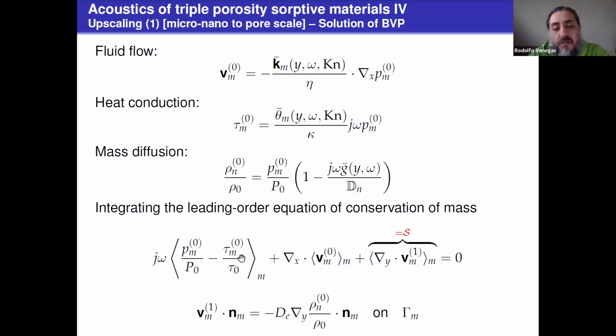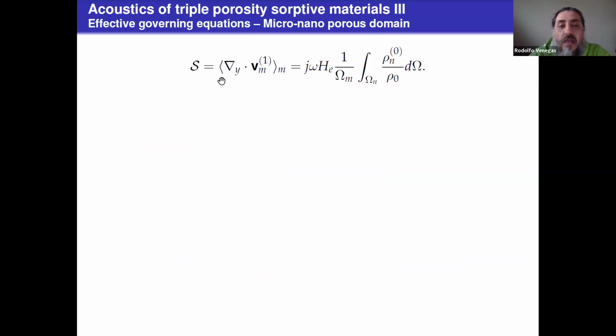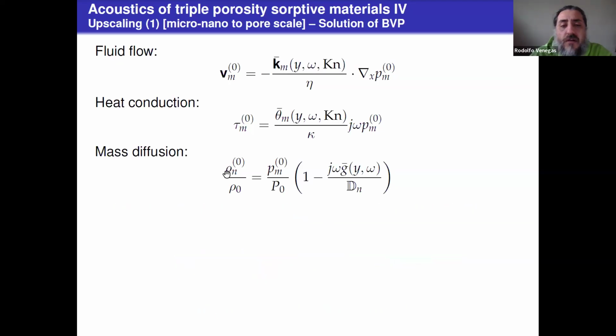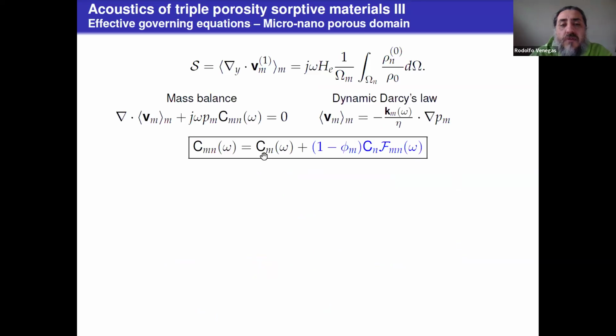So we take the average of this equation, and then we identify the source term. And this is very important because normally this term is zero for conventional materials, but in this particular case, we have the effect of what's happening at a smaller scale coming from this term. And in particular, this term can be written in this way. And then when we take the average, we use the divergence theorem, and then we can write this divergence of velocity in terms of rho n, and rho n is already known, which is given by this expression here.